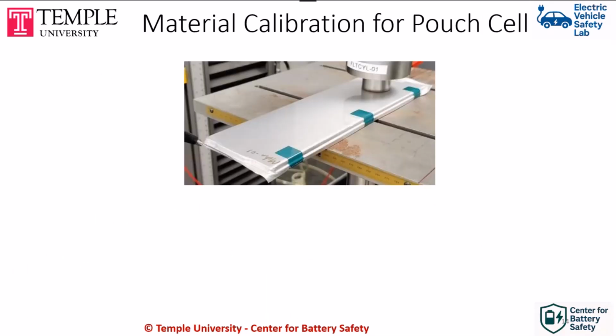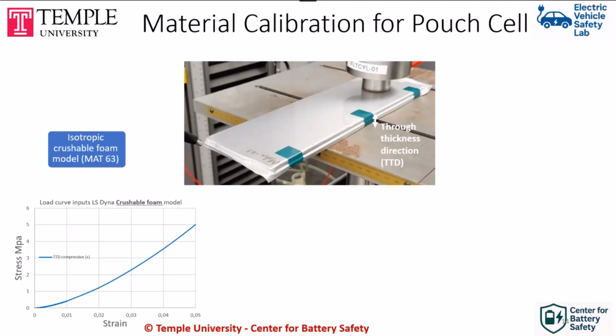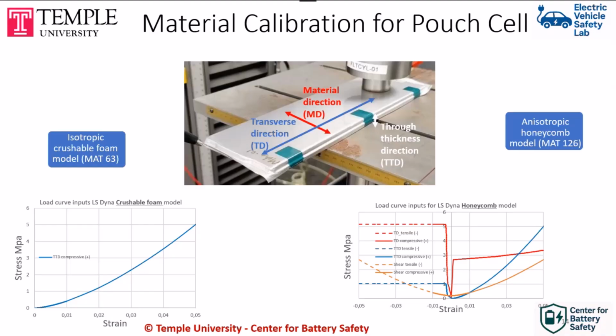Now, once we have all of these tests, in the very beginning we used MAT 63, and that was good enough for predicting the through-thickness crush behavior. But nowadays we use MAT 126 honeycomb. So we calibrate the properties separately in tension and compression in 3 normal directions, and then in 3 shear directions. And then we have 9 curves, and this makes the basis of the quasi-static material model at room temperature for 0 state of charge for the battery.